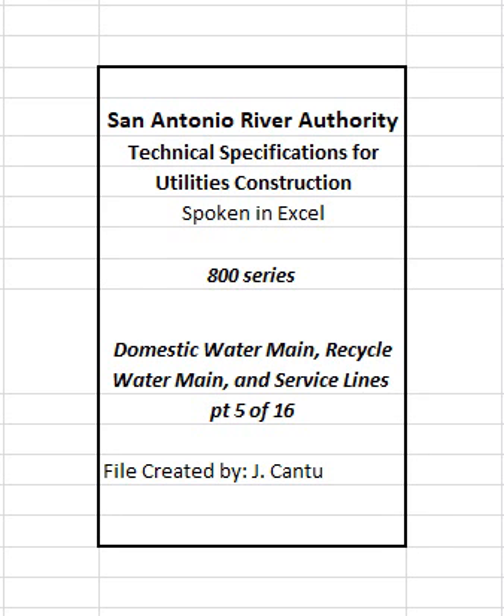The film shall have a dielectric strength of 800 volts per mil of thickness per latest ASTM D149. Chemical. The film shall be chemically inert, with a moisture absorption rate less than 0.01% in 24 hours. Marking requirements. The polyethylene film supplied shall be clearly marked, at a minimum of every 2 feet along its length, containing the following information: manufacturer's name or trademark, year of manufacture, ANSI/AWWA C105/A21.5-2010, minimum film thickness and material type, applicable range of nominal pipe diameter size, and warning: corrosion protection, repair any damage.